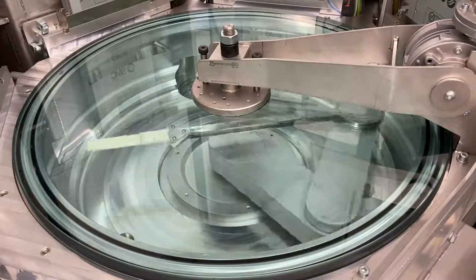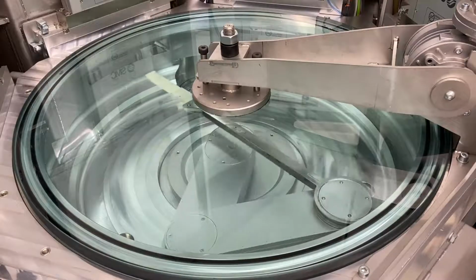The 2 deposition chambers: the first one is a more standard magnetron sputtering chamber. It has 5 sources. You have 2 RF, 2 DC, and 1 HiPIMS source. You can do temperatures up to 1000 degrees, and you can have atmospheres of oxygen, nitrogen, and hydrogen as well.